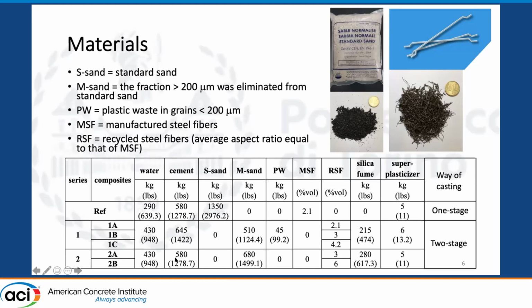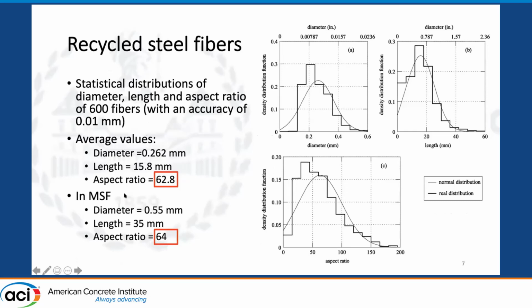We used the same content of water, and the same content of cement as the reference. So we didn't increase the cement, but to maintain the water binder ratio, we added a larger quantity of silica fume. In this case, we used only modified sand without plastic waste. These are the series of FRC we used, and here you have in particular the properties of recycled steel fibers. Obviously, you don't have the same diameter and the same length of these fibers. And here you have the distribution regarding the diameter and the length of the fiber.